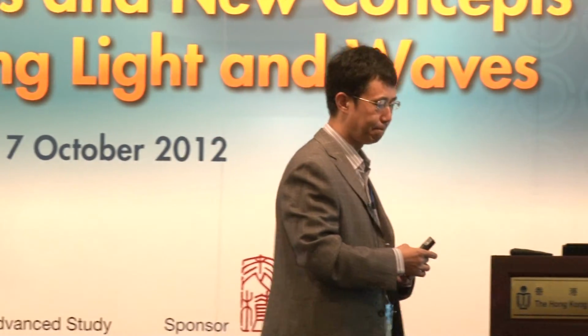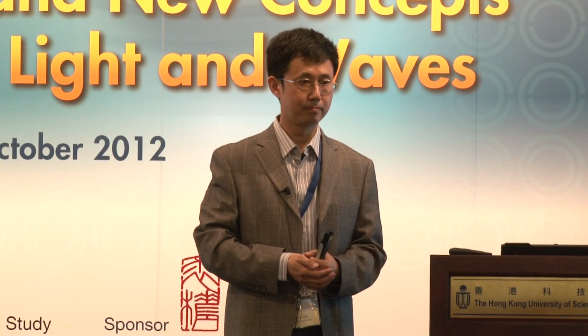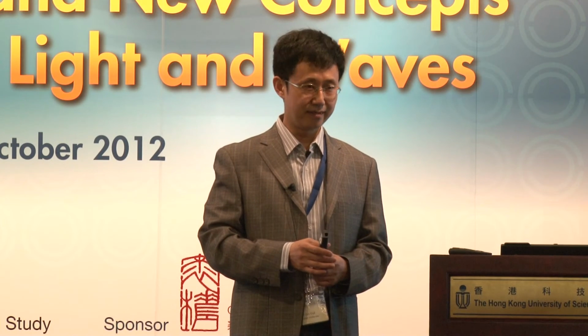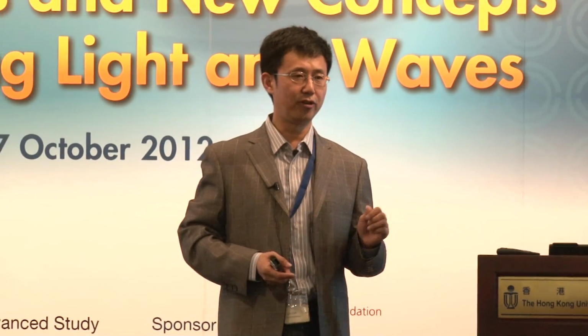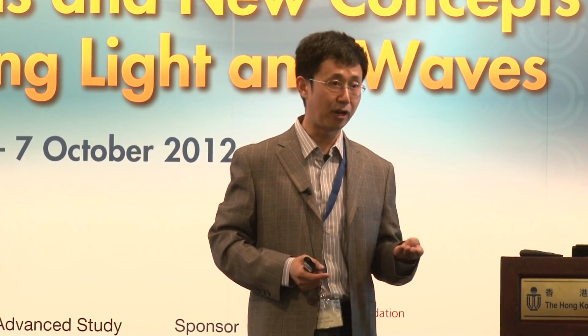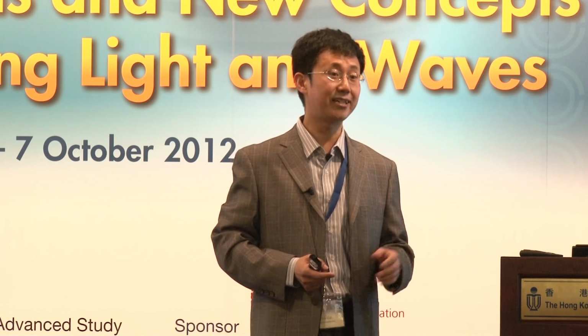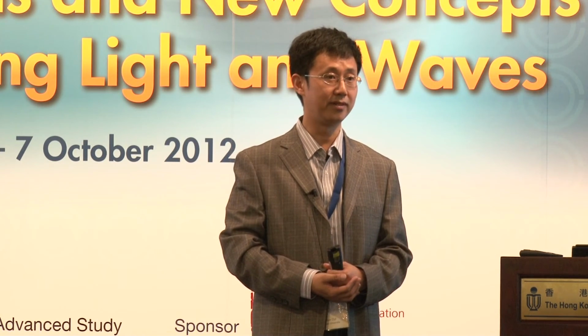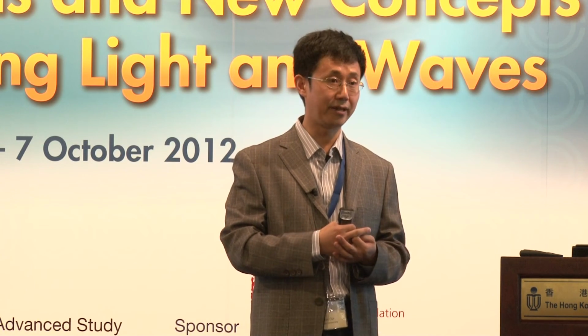Thank you. About the first part, the anisotropic zero-index materials. You use mu to be zero in the propagation direction in the cylindrical and Cartesian case. But I would guess that would work as well if you have epsilon zero for that case. Yes. But wouldn't it be easier to get epsilon zero rather than mu zero? For epsilon or mu, that depends on the TE polarization or TM polarization. So if you use TM polarization, you can. So it's easy to get epsilon z equal to 0, no problem. For the 3D case, we have designed both epsilon nearly 0 and mu nearly 0.